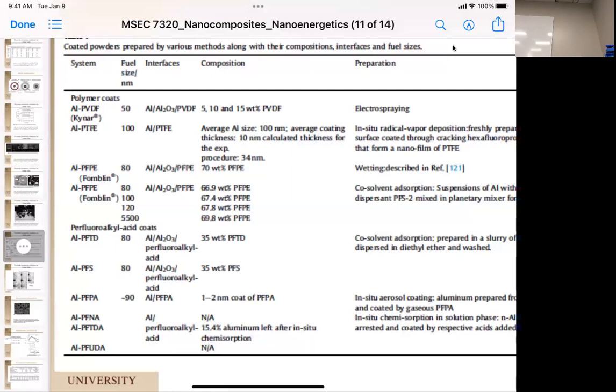And when they were able to do that, they were able to get nice dispersions. Probably a little too much Teflon in some of these right here. Notice they all have aluminum oxide in them, because there's always a little bit of aluminum oxide. We have to account for that. In fact, an 80 nanometer size aluminum particle has only about 80% combustible aluminum. So a lot of them do these macroscopic ones where they have aluminum oxide.